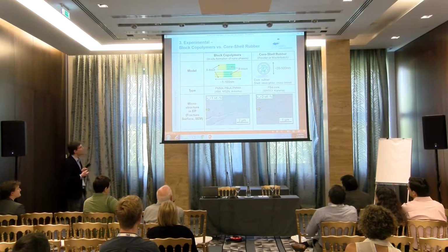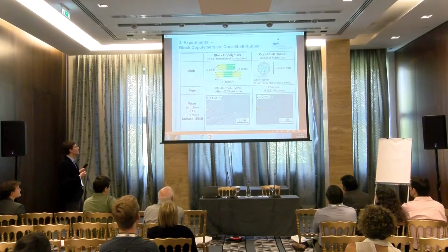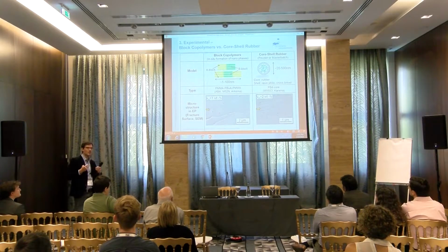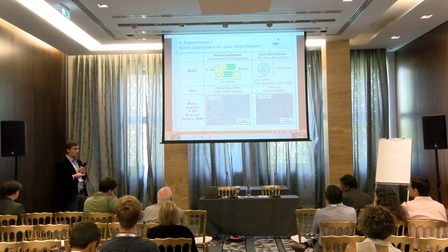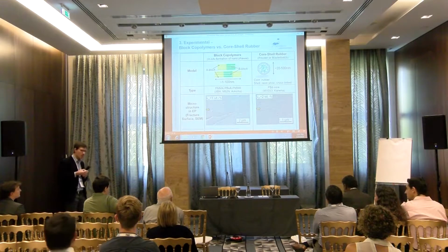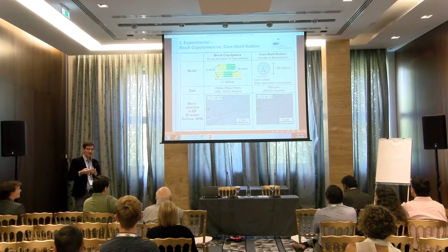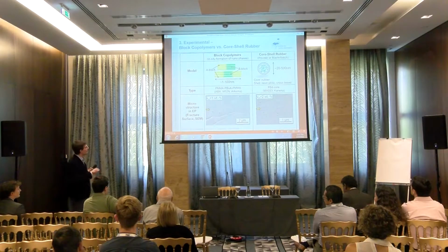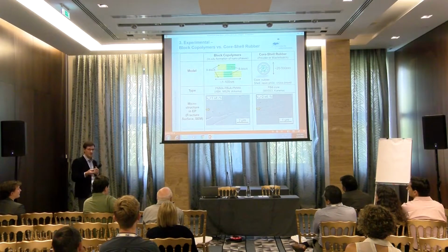The block copolymer we used is a triblock copolymer. A block copolymer is one material made out of two or more constituents, polymers which are usually not compatible, but you can, via chemistry, merge these polymers and create a macromolecule which has, for example, an epoxyphilic and an epoxyphobic part. And now imagine you put that in your epoxy, you will have, driven by thermodynamic forces, some kind of phase separation, right? This phase separation is, for example, shown here. Yeah, so this is the nice thing about copolymers. You don't have to have any kind of dispersion efforts.